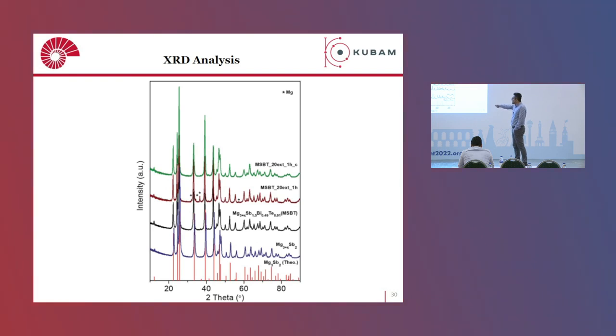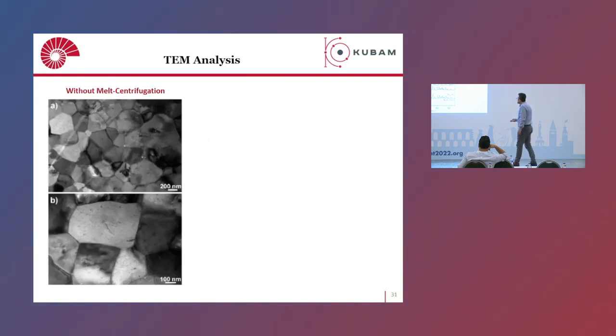Then we add a little bit of bismuth and tellurium to tune the electronic properties, and then add extra magnesium. By adding extra magnesium, you can see that sometimes, even when we introduce this melt centrifugation, there is some residual magnesium left in the microstructure. You cannot 100% remove it with this, but we couldn't always remove it 100%. So it depends on the experimental conditions.